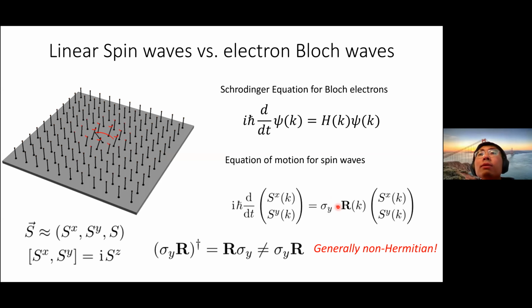We know the band structure and the topology of the electronic band very well. But here we are facing a problem: for this kind of spin wave Hamiltonian, because the matrix that governs the time evolution is not Hermitian, the structure of the topology seems to be slightly different from the electronic case.